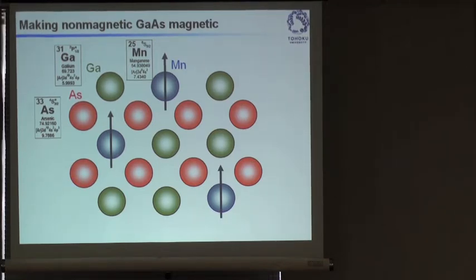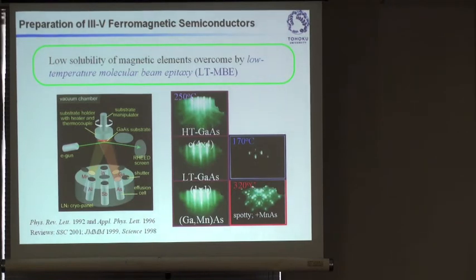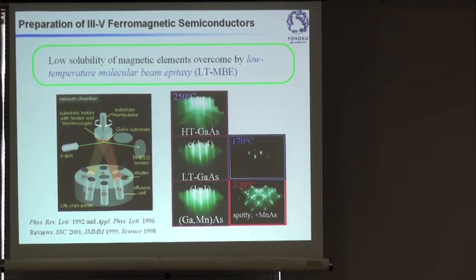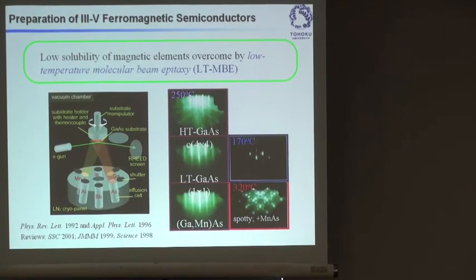So first of all, we needed to synthesize the material, and the method we used was low temperature molecular beam epitaxy. We were lucky to find that there's a temperature window. This is 250 degrees C. Usually for gallium arsenide, we use 600 degrees C to grow the material. But we reduce the growth temperature to maintain the potential landscape on which manganese can find its site, which is the gallium site. And the temperature is not so low that we get polycrystalline growth.